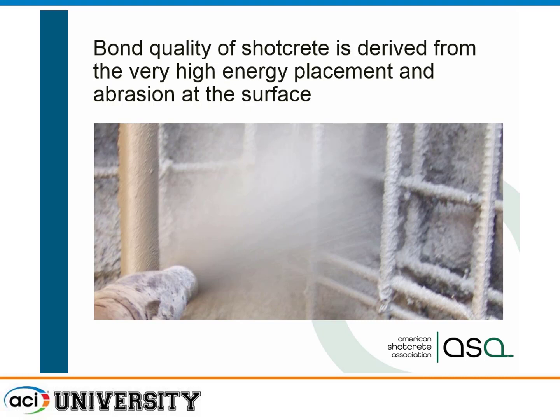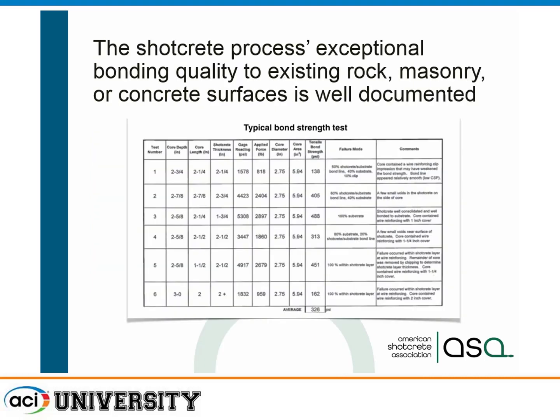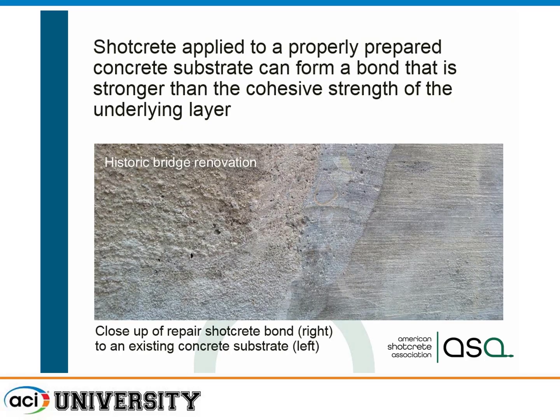And why are we getting such good bond? High energy placement. I guess I got ahead a little bit in terms of the slide, but 138 was the lowest here, but you can see tensile bond strengths of 400 psi, 450. Here's a lower one, 162. Generally it's very easy to get roughly 150 psi. If it's less than that, there's some problem with the surface prep or with the placement or the material in some way. And here's an existing substrate. Here's where we shot against it. And it's very difficult, except for color, to see that we have any kind of interface there.